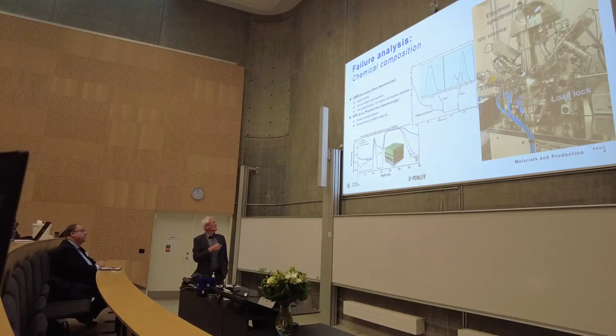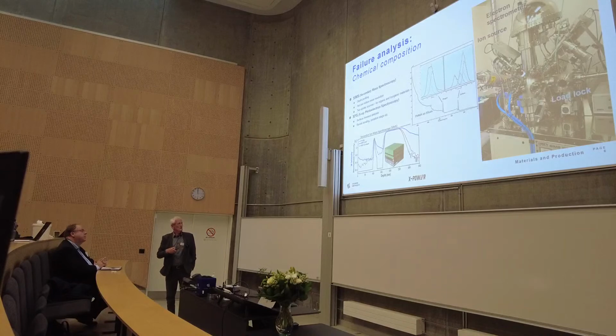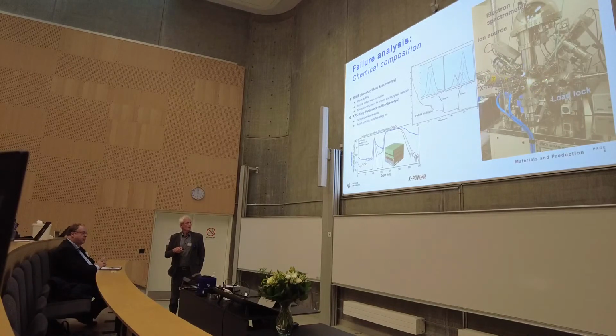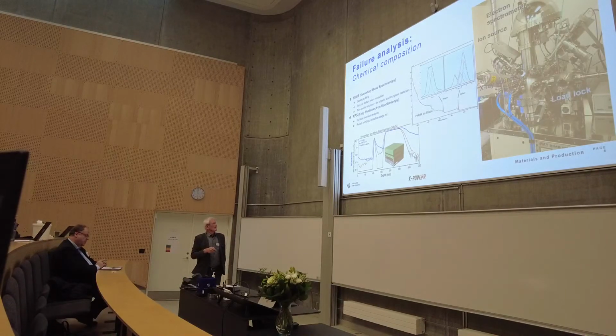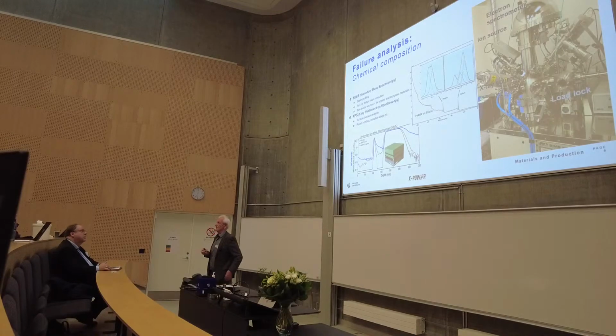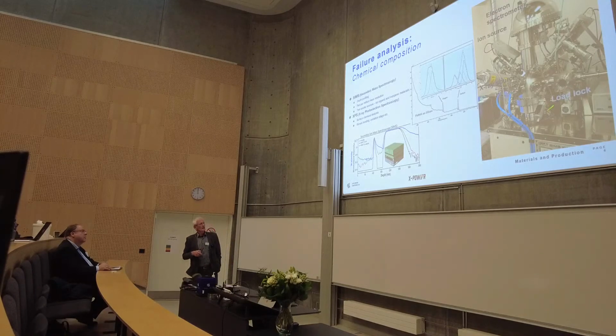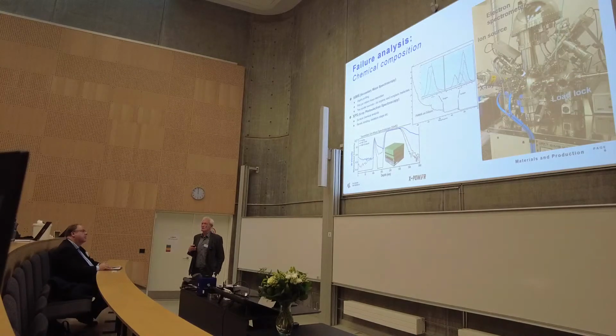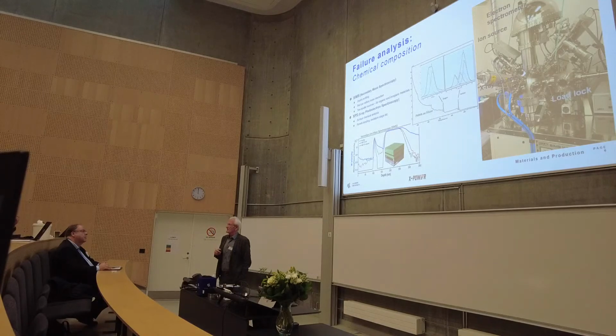You could also look with X-ray photoelectron spectroscopy. You send in X-rays from the source here, and you look at the electrons coming out to the spectrometer and analyze their energy. This is just a simple example of a polymer put onto silicon. You have some carbon, you have some oxygen, but you can also resolve very sharp details in these spectra, and this tells you something about the chemical bonding, so we can figure out how the atoms are bonding to each other. Everything is with a load lock, and you can put things in. You have two ion sources, so you can use both organic and inorganic materials in the system.